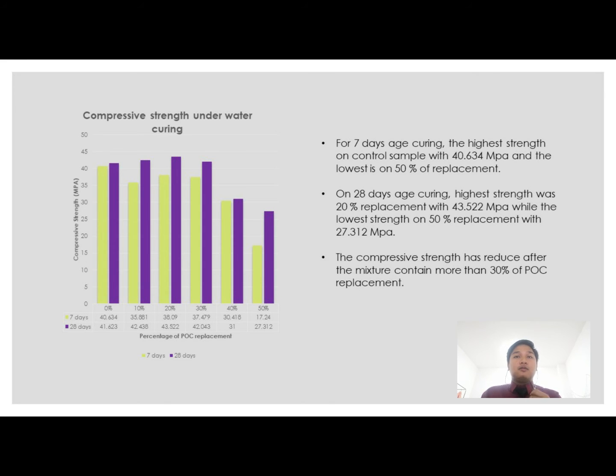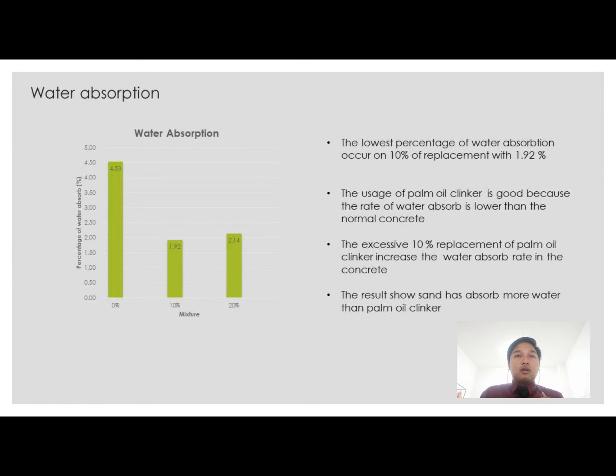Water absorption. For the water absorption, the 10% replacement recorded the lowest percentage of water absorption with 1.92%. The usage of palm oil clinker is good compared to normal concrete because the rate of water absorbed in 10% replacement is lower than the normal concrete. The excessive replacement after 10% of palm oil clinker increases the water absorption rate in the concrete. We can see the water absorption percentage increased after 10%. The 20% replacement recorded 2.14% water absorption.